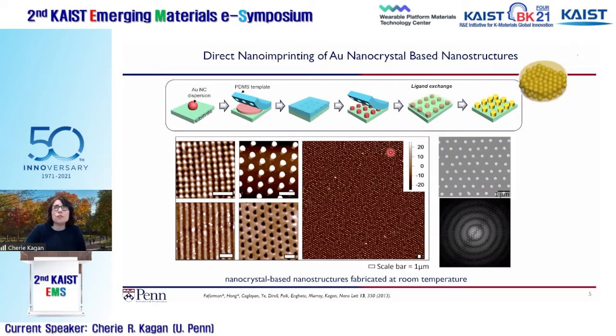Each one of these pillars is in fact made up of many different nanocrystals. And with that, you could use the complexity of lithography and create, at the time, simple structures of pillars with square and hexagonal motifs, lines, and nanohole arrays. And the idea is that we could make these structures. If you look at each one of these pillars, you can see they're actually made up of many nanocrystals. But this simple process actually gives us fairly high reproducibility over a large area in creating these patterned structures.